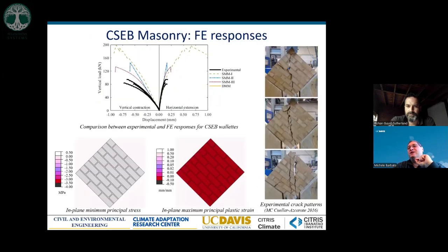But then we did the same exercise with compressed and stabilized wallettes. Again, you can see on the right side the end results of the experimental testing. The black lines here correspond to the experimental results, and then the other colored lines are the results coming from the simplified micromodel, which are not good. We are overestimating by up to 200% the value of the load that this wall can take when loaded diagonally.